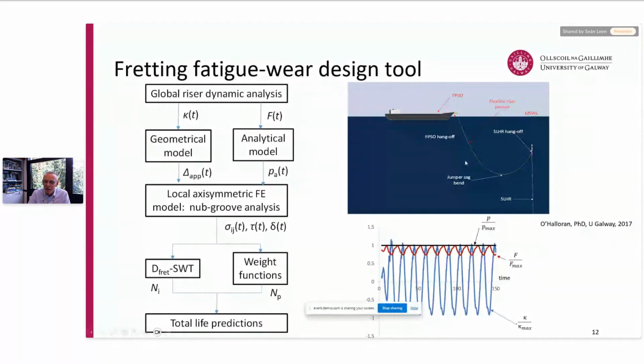And we've looked at a bunch of design load cases for that with our industry partners, Wood actually. And then you can see in the bottom right some of the multi-axial loadings: pressure is constant, the axial load F varies as a function of time, and the curvature varies as a function of time. That comes from a dynamic beam element model called FlexCom, which we've used for global riser dynamic analysis. And then we've used a geometrical model that I'll show you in a moment, which allows us to take the global curvatures as a function of time and convert those into displacements that we can apply to the local axisymmetric FE model. We've also taken the axial loads, and we can use them with an analytical model to estimate the pressure between the nub in the nub groove contact region.